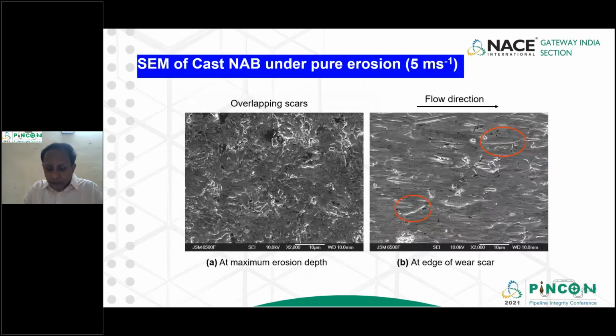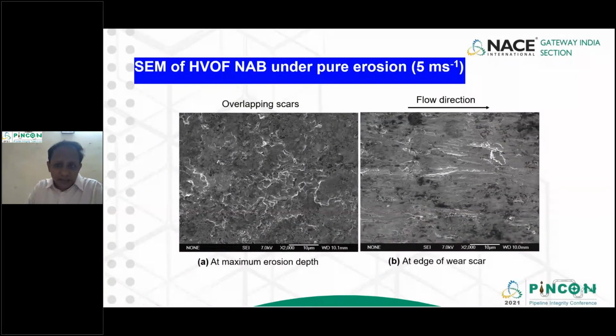Then you could see here, when the liquid is hitting with a sand particle, it creates some edge wear on the substrate. You can see these two very distinctive features, it's creating a wear scar. Similarly, in the flow direction, when a sand particle goes and hits, it removes the material. This is what we observe.